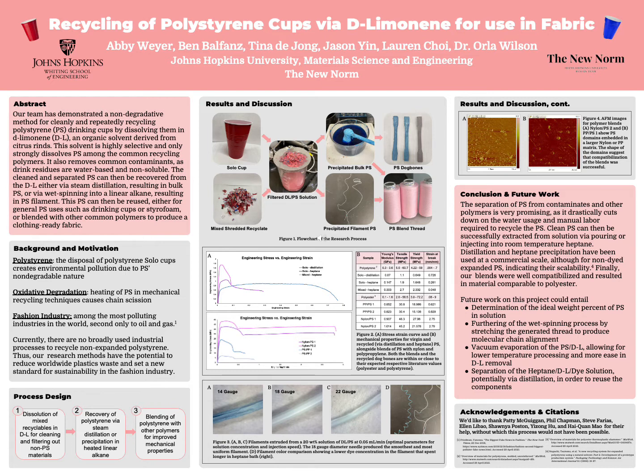As you can see, both blends take the form of one polymer forming the bulk matrix and the other forming small discrete precipitations, which is to be expected for compatibilized blends and indicates their success. In conclusion, we believe that our work has been highly successful. Our ability to non-manually separate and clean polystyrene and then reprecipitate it is very promising. Additionally, similar processes have been performed commercially, indicating the ability to scale our process as well.